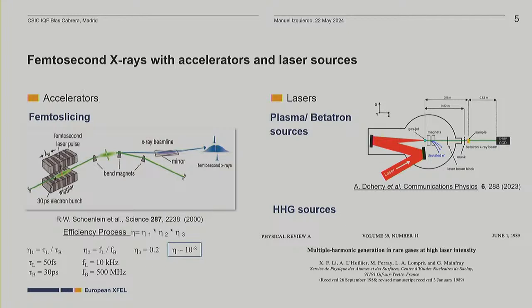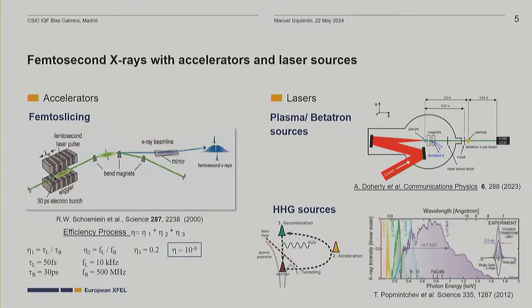In this respect, if you want to understand this, you need to have, from the laser side, higher photon energies, and this has been achieved in two different ways. On the one hand, you have plasma betatron sources that produce X-rays in what we call the X-ray regime, so 10 kilo electron volts or so. And on the other hand, up to a few hundred electron volts using harmonic generation, that you see here, this paper from L'Huillier, who got the Nobel Prize last year. This technique is what has allowed to go above 1 kilovolt.